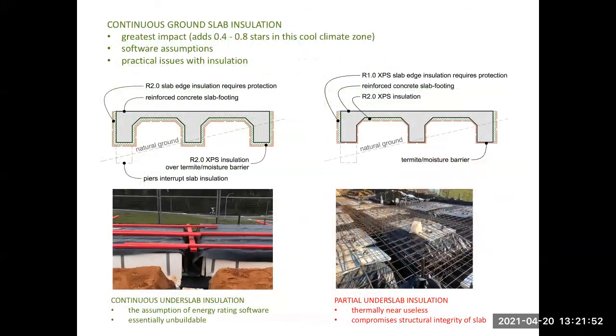Now, slab insulation is the one thing in the Mullum Creek houses that has the greatest impact of any upgrade measure. So this typically adds between 0.4 to 0.8 stars. And this is using R2.0 to R2.5 rigid insulation under the slab, like XPS, extruded polystyrene. The slab insulation that we're talking about is not waffle pod insulation.